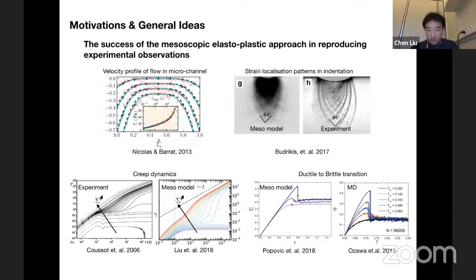And then, so this model has achieved several successes in describing the rheology of soft materials. So here are several examples. First one is the description of the flow of colloidal system through a microchannel given different pressure gradient. So in this figure, it plots the velocity profile as the position across the microchannel. So the red crosses are the experimental data, and the blue circles and lines is the prediction from the mesoscopic model. And you can see that it's quite a good agreement there.